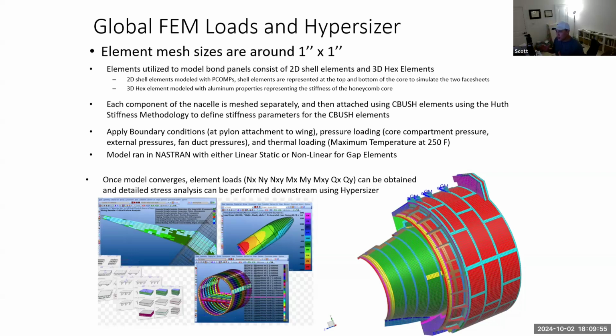After each component is meshed, they're attached together with C-bushes. C-bushes are basically 6 degrees of freedom springs that are used to attach components together in finite element software. After you do that, you apply boundary conditions because the component is a static component, right? It's moving in the air, but under loading, it's static. It's a static analysis. We're not doing dynamic analysis. So you need to apply boundary conditions, typically at the pylon attachment to the wing. In terms of loading, it's typically pressure loading: core compartment pressure, external pressures, fan duct pressures, and then thermal loading, because as you can imagine, you're at the engine region, so you're going to see high temperatures as well.